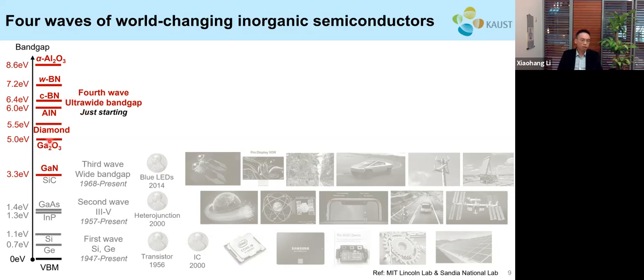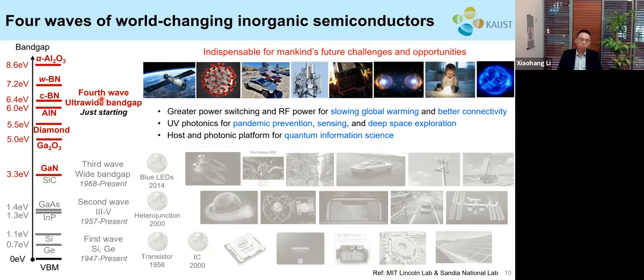They have a much larger bandgap, up to 8.6 electron volts. They include materials such as aluminum nitride, boron nitride, as well as oxides such as gallium oxide and aluminum oxide. And because of the much larger bandgap, they can handle a lot more power compared to any material below. And that is essential to improve the energy efficiency of human society, to slow down global warming and enhance connectivity beyond 5G.